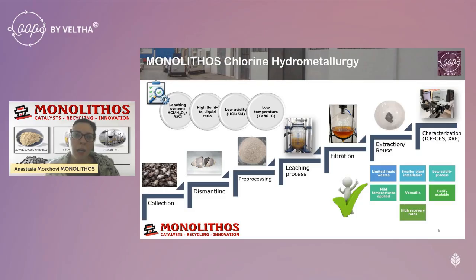Finally, either by precipitation or solvent extraction or other purification techniques, we can get the metals with high purity out of the solution. And of course, we identify the purity and the recovery rate with physicochemical characterization. In our case, we use mainly XRF and ICP analysis.